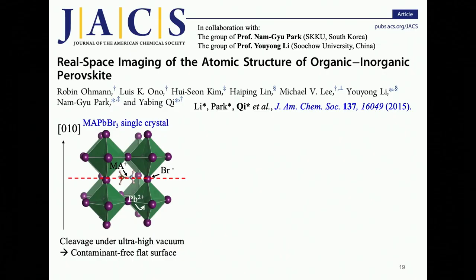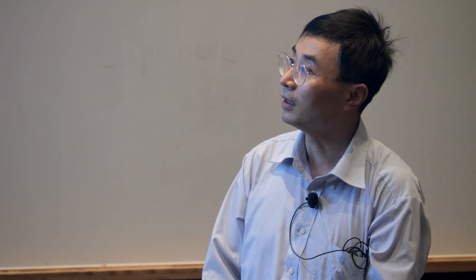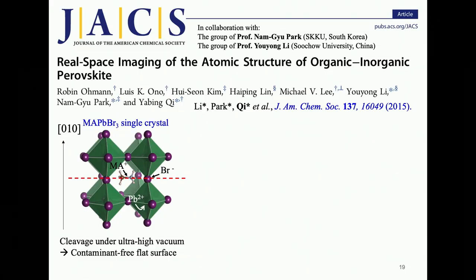The model shown on the left is the typical crystal structure of the perovskite materials. And in the case of MAPbBr3, each Pb lead ion is surrounded by six bromine ions, forming the so-called PbBr6 octahedron. Then eight such octahedra form a cage at the center of which the MA cation is located.